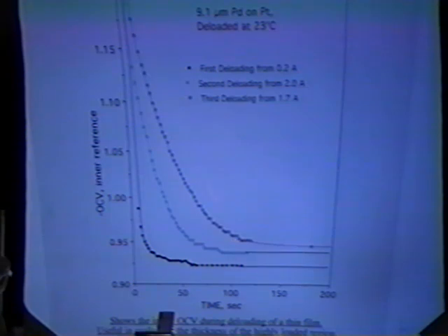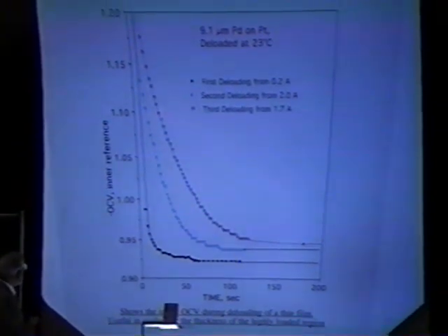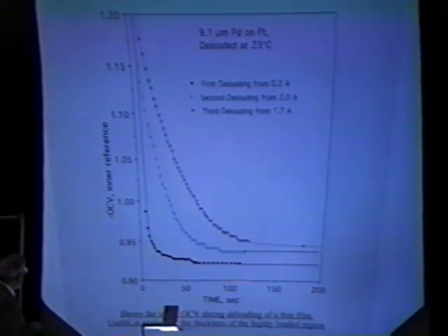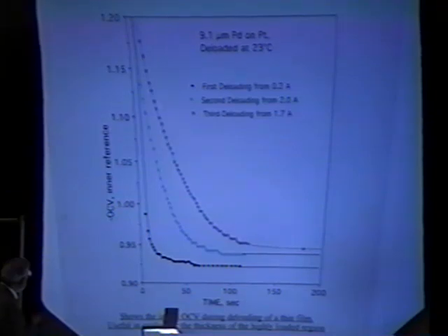This is the curve that's most interesting because it shows the indirect relationship between the surface composition and the composition during deloading, but in the beta phase. See, this is the beta phase coming down. This is somewhat typical. The beta phase deloads, and then it goes two-phase and becomes constant. The shape of the curve in this region is very important, as you'll see.